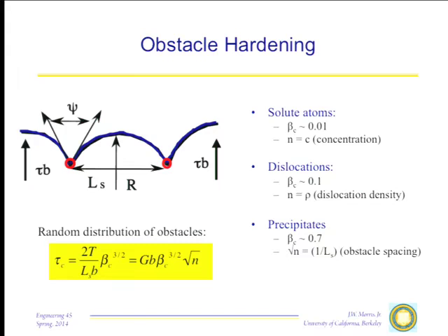If you deform a material so that you increase the dislocation density, in almost any material, the strength that you get out, critical resolved shear stress, is going to turn out to be proportional to GB root rho, where rho is the dislocation density. And that applies in material after material and situation after situation. Very useful and also kind of surprising if you look at the complexity of the behavior of arrays of dislocations.